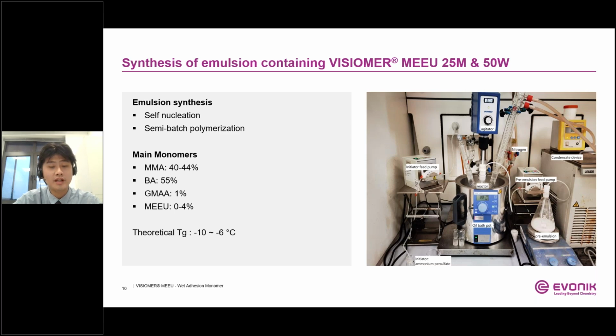Here is our guide formulation on the left side. We used a self-nucleation and semi-continuous emulsion polymerization process. The high glass transition temperature monomer is MMA with an addition amount of 40 to 44%, and the low glass transition temperature monomer is butyl acrylate. The addition amount is fixed at 55%, and 1% methacrylic acid is added to maintain the stability of the emulsion. And the active content of MEEU varied from 0 to 4%. It is a quite simple reference formulation.